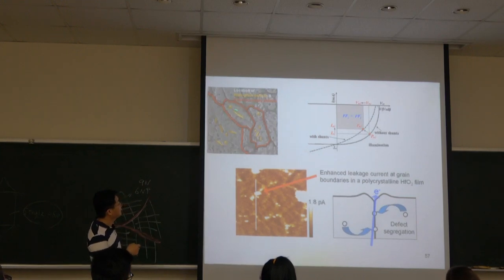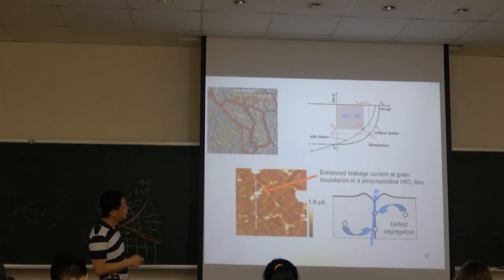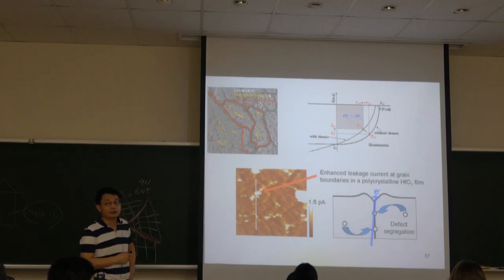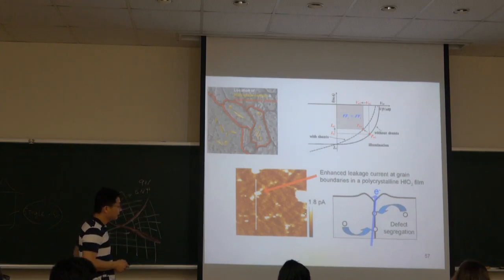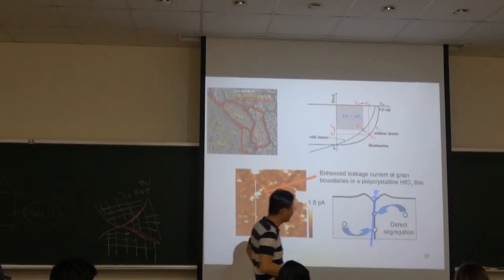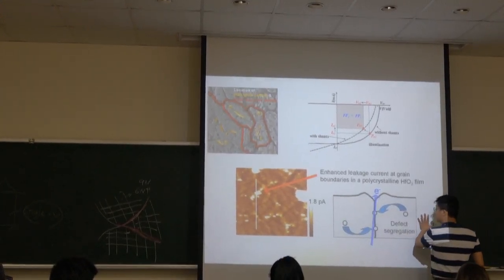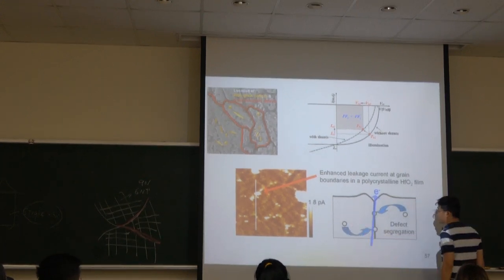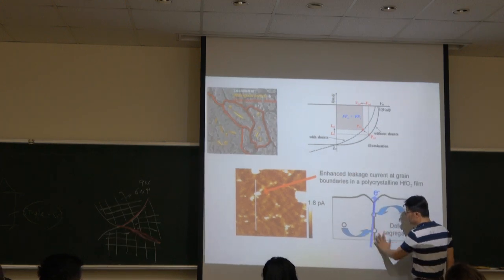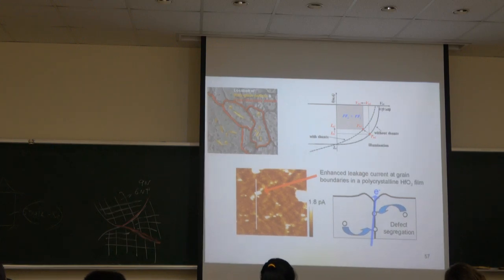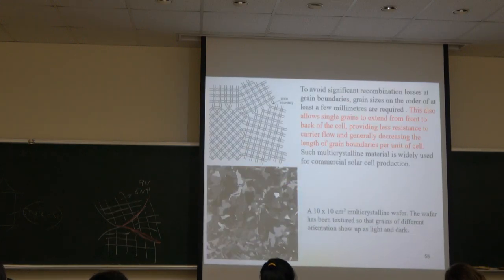So a lot of the grain boundary that we have to investigate, because for example, if we look at the characteristic IV curve, it looks like the fill factor is quite low, and then we have to further investigate the surface structure, and also maybe the IV curve, and maybe we have to cut a cross-section to investigate with TEM, to see the TEM of the grain structure's distribution, see what is the main cause.